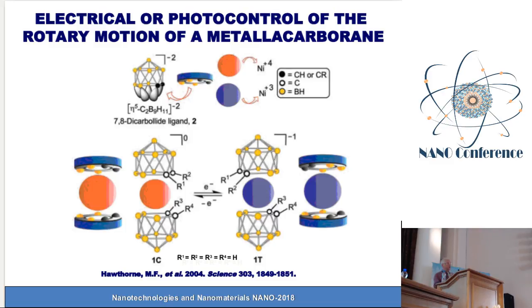Actually, all metallocarboranes can rotate around the axis, but the efficacy and the energy of such a motion depends upon the metal coordinated by the boron clusters. It was found that the complex of nickel gives best results because the rotation, controlled rotation, can be achieved by changing the oxidation state of nickel from +3 to +4 and the reverse from +4 to +3. And this is connected with the changing of the conformation of the molecule.